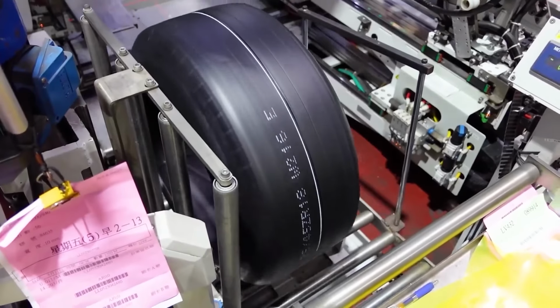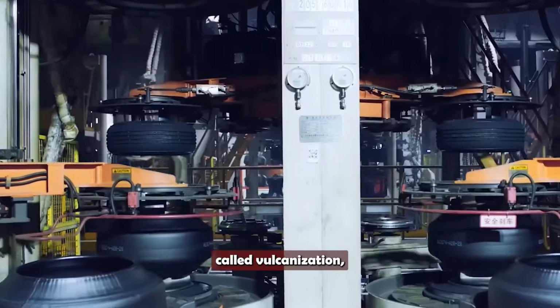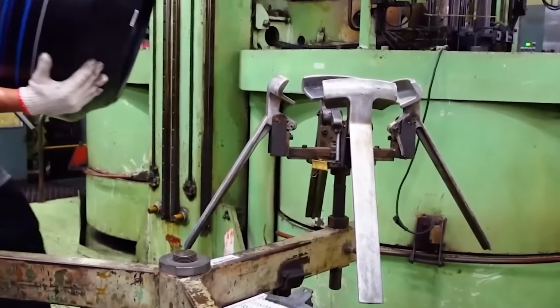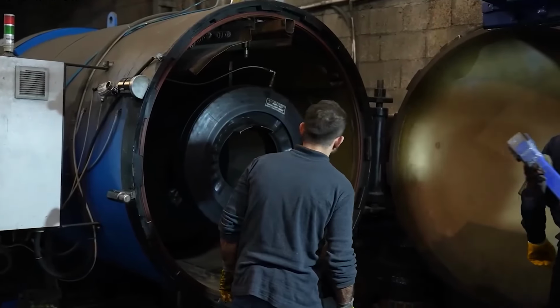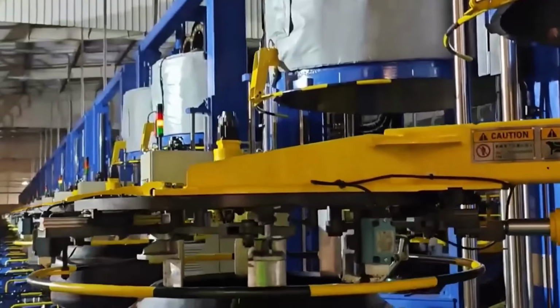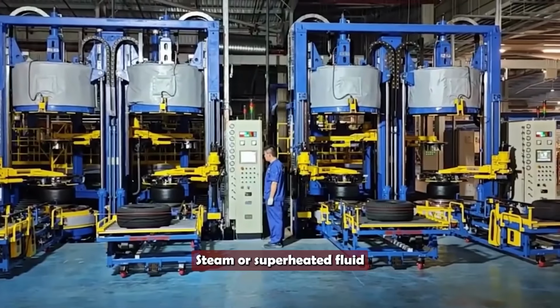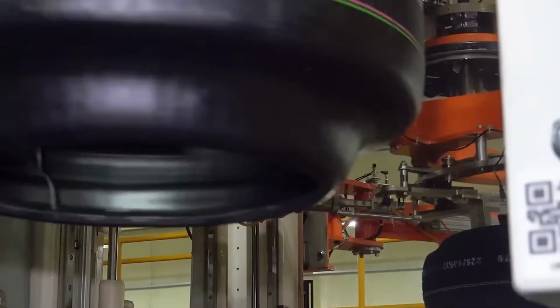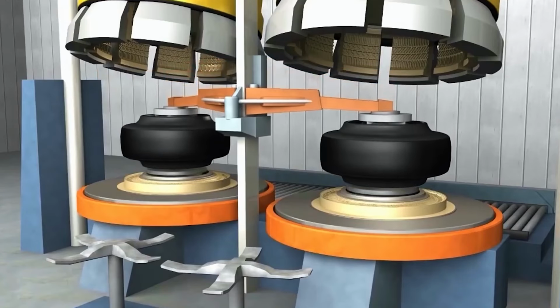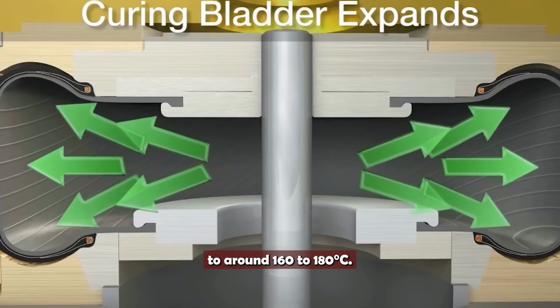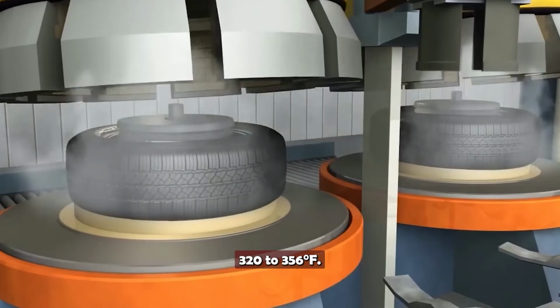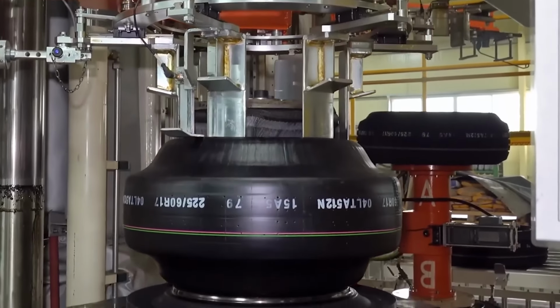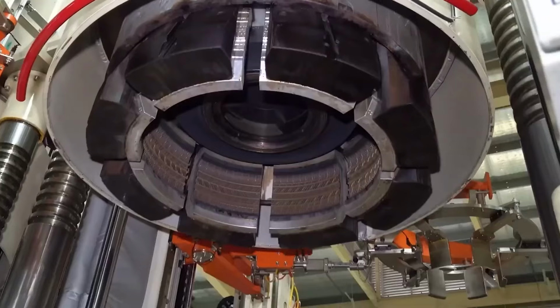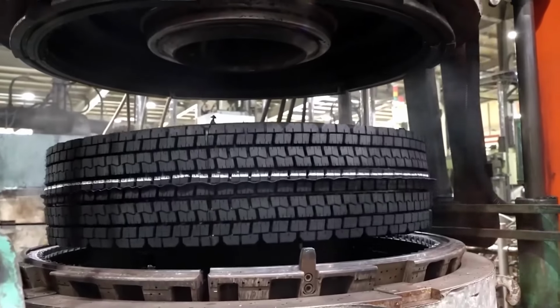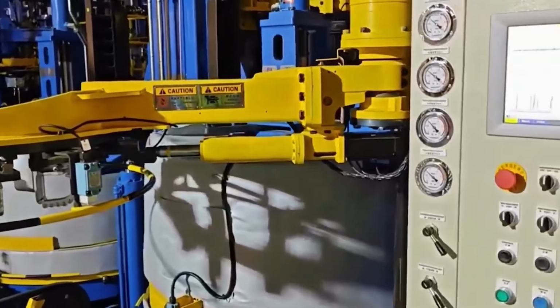But in larger, high-tech plants, the tread is formed during a process called vulcanization, and this is where the magic happens. The unfinished tire is placed inside a two-piece metal mold that's engraved with the exact tread pattern. The mold clamps shut like a giant waffle iron, and then things heat up. Literally, steam or superheated fluid is pumped into a flexible bladder inside the tire, forcing the soft rubber outward until it presses tightly into every groove of the mold. At the same time, the mold is heated to around 160 to 180 degrees Celsius, 320 to 356 degrees Fahrenheit. This heat triggers a chemical reaction between sulfur and the rubber molecules, locking them into a strong elastic network. What was once soft and pliable is now tough, resilient, and ready to handle the road. This process doesn't just give the tire its final shape, it's what gives it its soul.